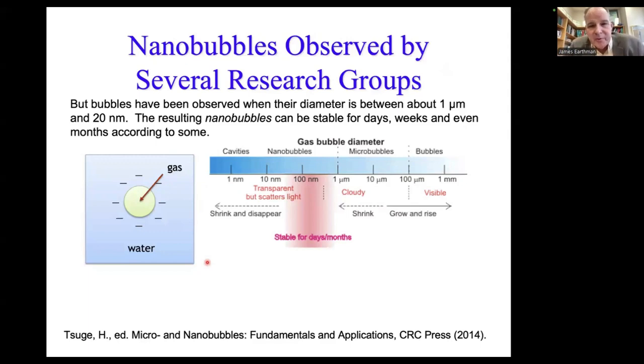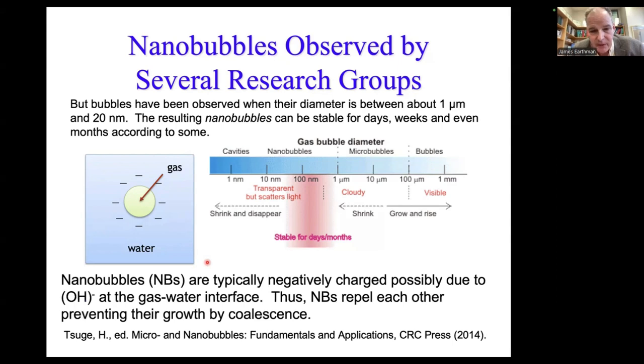So again, nanobubbles were observed by several research groups. There were a lot of groups in Japan for some reason. I'm not sure why so many groups are working on this in Japan, but a lot of groups in Japan were working on what they were calling nanobubbles. And they were reporting that nanobubbles tend to be around 20 nanometers to 1 micrometer in diameter, and they can be stable for many days. They were already seeing this long-term stability. And the nanobubbles were typically negatively charged, as I showed you with the zeta potential. And a lot of people were attributing this to OH ions, which are negatively charged. In deionized water, that's about all you've got in the water that's negatively charged. So that kind of made sense to me.